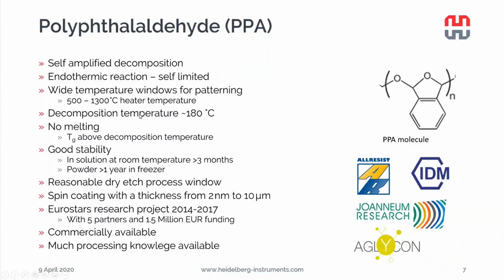The decomposition temperature of this PPA is about 180 degrees Celsius, and the glass transition temperature is above the decomposition, so we don't get any liquid state. So some of you might ask, well, if decomposition temperature is 180 degrees and we use a temperature window of 500 plus degrees, what does this mean?